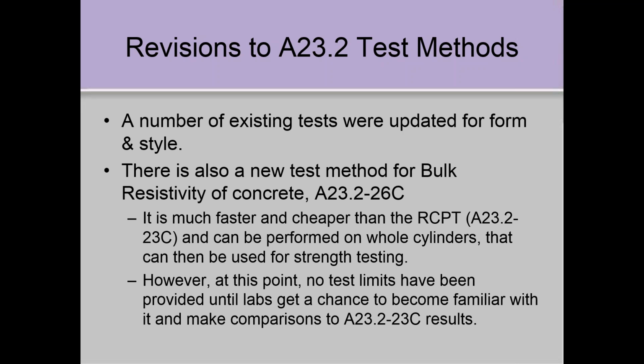And the reason is, eventually, hopefully, it might replace the A23.2 23C, the rapid chloride permeability or the Coulomb test. It is much faster. And you can also test whole cylinders with this method. You don't have to cut discs out of it. So you could actually take a cylinder, measure the resistivity end to end, and then put it in a testing machine and break it for strength.